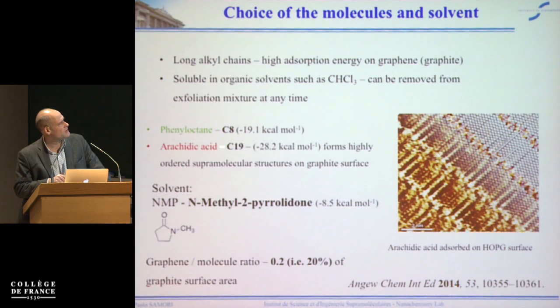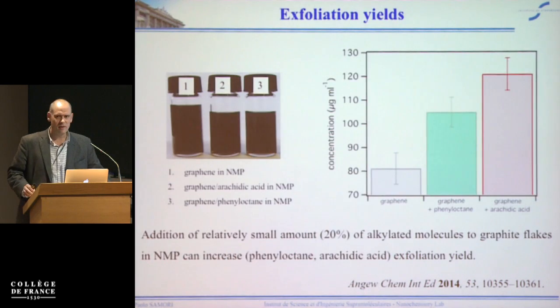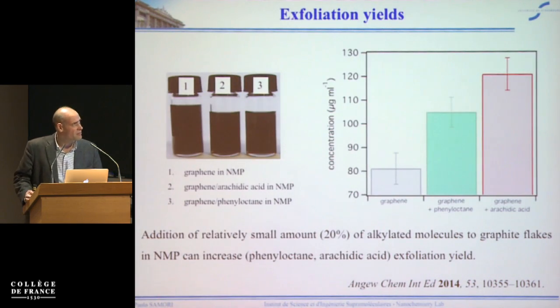We focus our attention on C8 and arachidic acid C19. Of course, the energy of absorption of graphene should be higher than that of the solvent, that is NMP, otherwise it makes no sense to use the alkanes. Now, this is an example of arachidic acid forming nice lamella on the basal plane of graphite, and we have the same result on CVD graphene as well by STM.